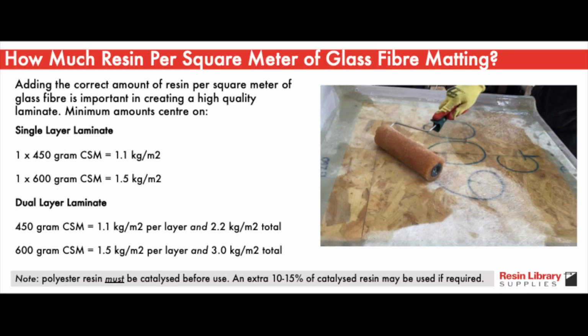Adding the correct amount of resin per square meter of glass fiber matting is important in creating a high quality laminate. Depending on the grade of matting, minimum amounts center on 1.1 kilograms per square meter of 450 gram matting and about 1.5 kilograms per square meter for 600 gram matting.